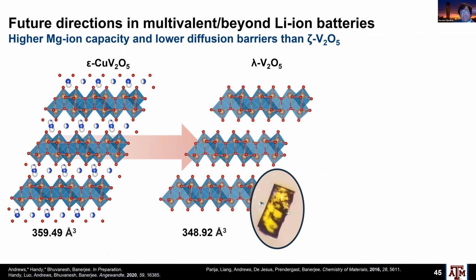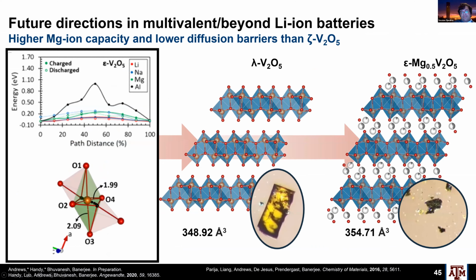Here's another structure. Again, we can grow single crystals of this. This is not a one-off fluke. We're again pretty excited about this whole family of compounds. Epsilon copper V2O5: we can take copper out and stabilize lambda V2O5, and it's a fully van der Waals compound. It can be cleaved by Scotch tape. We have a collaboration with Shing Tu's group at Texas A&M working on these structures.